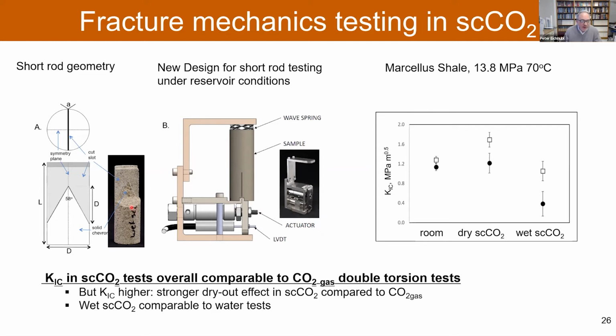Now, it's a little different testing geometry because it has to be small enough to fit into the pressure vessel. It uses a different fracture geometry. It basically wedges the sample along its axis. It's not the double torsion that we use in Olson's lab. It's called short rod geometry. There's a chevron notch here, and then it gets wedged open. It allows us to measure the fracture toughness. It does not allow us to measure the subcritical index.